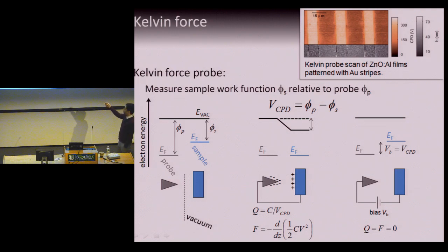Now I have a negatively charged probe electrode and a positively charged sample electrode, and there's a force between them because there are electric field lines extending from this surface to this surface. Now, if you have a way of measuring that force, if you have a transduction mechanism, you can then do something to measure the difference in work function. You can apply a bias. And if you apply a bias that's exactly equal and opposite to the work function difference between these two materials, you cancel the buildup of force, you null out the force, and then you know what the difference in work function is, because it's exactly the bias that you applied. So this is a null measurement. You measure a force, you apply a bias, and you tune the bias until you've nulled out the force.